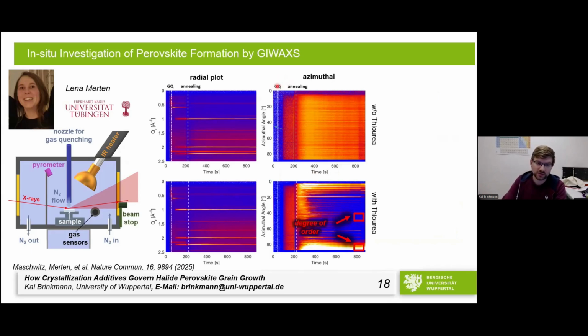Because when we started out with the perovskite spin coating, everything looked the same. When we did the gas quenching, basically doing the nucleation, what we thought was super, super important, everything looked exactly the same. And I have to say that here already the perovskite forms. So these points here, these are actually the perovskite. We'll see this in the next slide. And then eventually just the moment when we started the annealing process, that's the moment when the grains started growing, and that's the part when they started orienting.